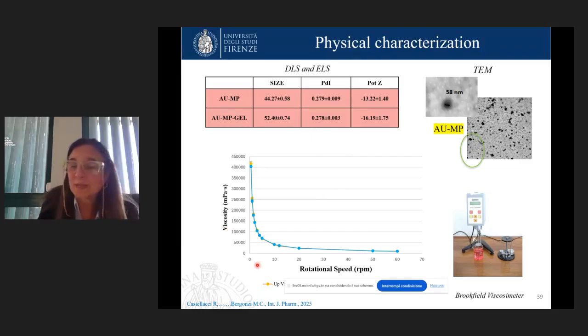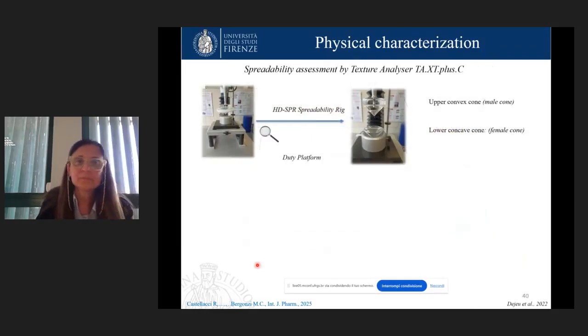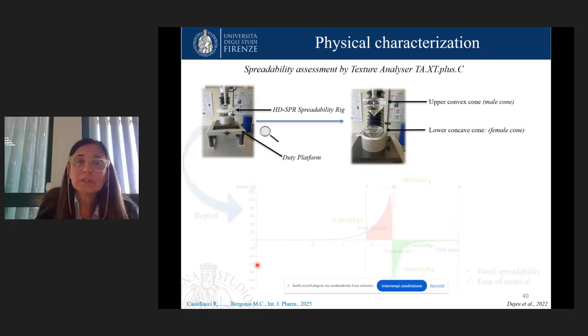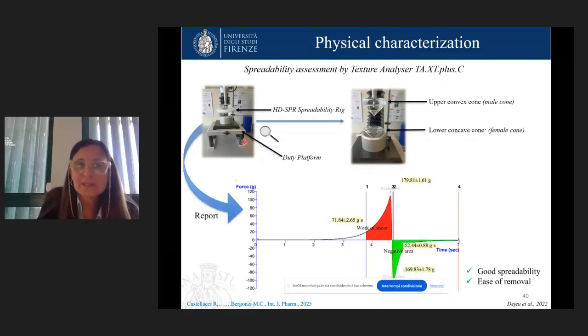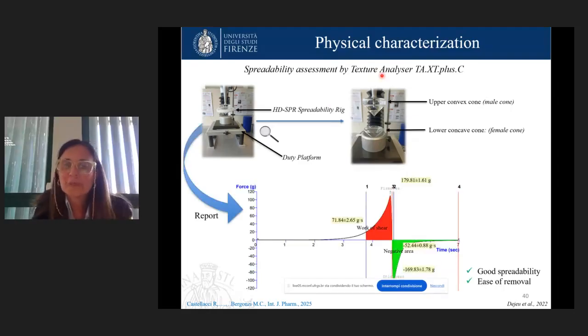is a pseudoplastic system. Also, the gel was tested in a texture analyzer to characterize the spreadability of the gel and the adhesion of the gel, important for adhesion to the skin. We obtained results that showed a good spreadability and a good adhesion of the gel, but also an easy removal from the skin.